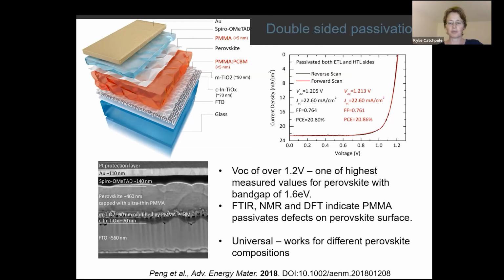Now, the interesting thing was it worked for a range of different perovskite compositions. So we tried this with a number of different perovskite compositions, and in each case, we're able to get a passivation effect. So that was very important in enabling us to just get a higher efficiency overall for any type of perovskite solar cell that we wanted to make.